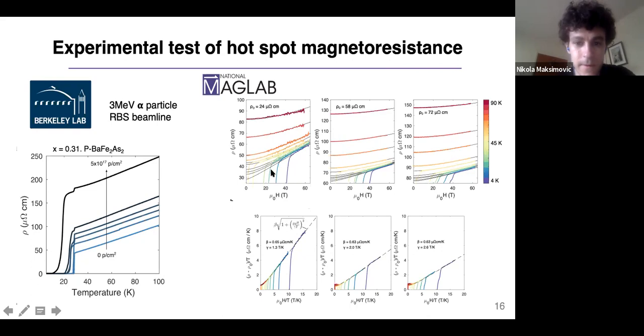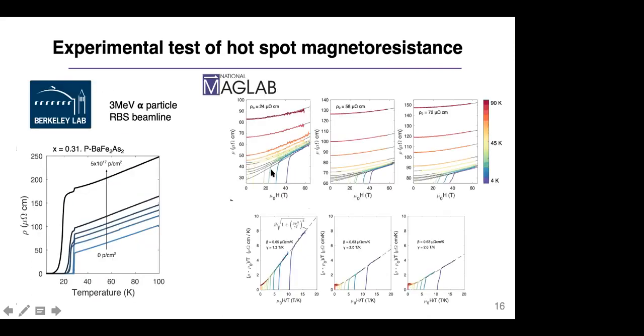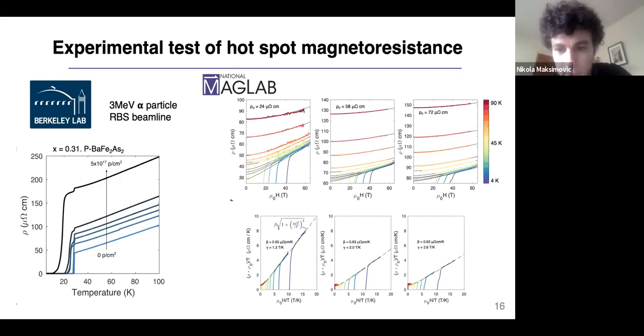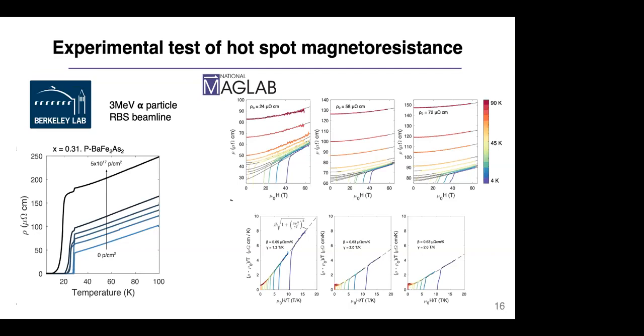Yeah, so for the magnetoresistance, when you go to very high field, are you getting an H square, or is it still linear? For magnetoresistance, when you go to a very high field, you see H linear behavior. Always. This is very different from the cuprates, because in the cuprates we did find the H square in very high fields.